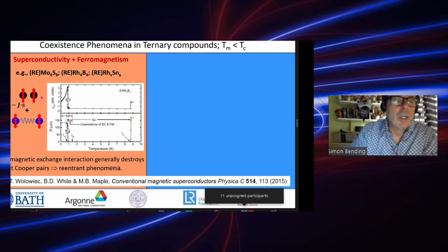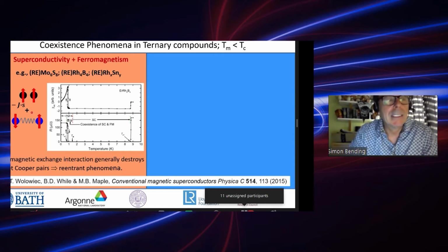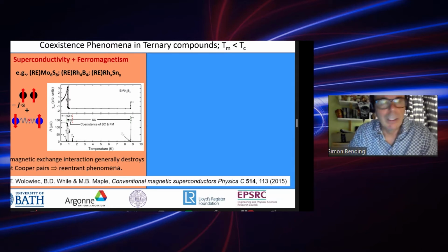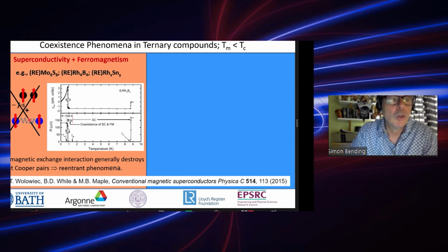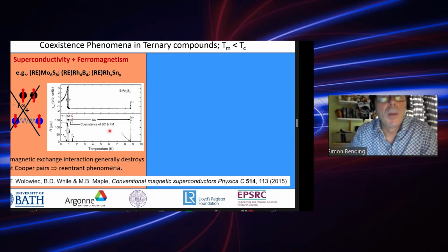Now, of course, as we're all aware, the coexistence of ferromagnetism and conventional spin singlet superconductivity is pretty unusual. Generally, this is blocked because the exchange interaction which aligns the moments in the ferromagnet tends to break the anti-aligned spins in the conventional superconducting pairs. So that's normally blocked. So this generally tends to lead to reentrant phenomena.